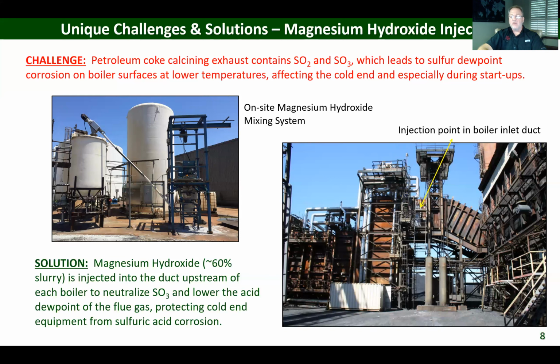That magnesium hydroxide reacts and neutralizes with the SO3 in the flue gas and effectively lowers the acid gas dew point, and really helps to protect the cold end equipment. We've really seen a lot of success with this over the years. We make sure we inject enough to coat the tube surfaces and really do a lot of neutralization, so that when we do a startup, we've got plenty of mag hydroxide on all the tube surfaces. But this has been a great system for us.